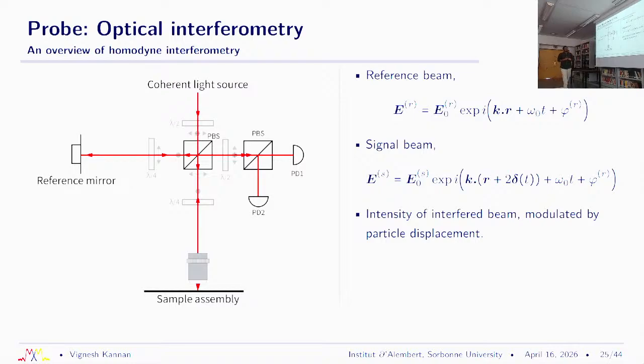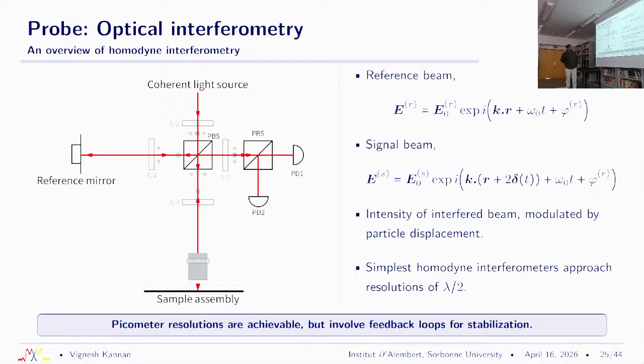Now the catch with a homodyne interferometer is unless you stabilize two laser beams, right, these are laser beams, unless you lock them to a particular phase, it's very difficult to get spatial or displacement resolutions less than half the wavelength of the light source we use, which is about 300 nanometers for us. 300 nanometers resolution is not acceptable for our experiment because the excitation is on the order of 1 to 10 nanometers. In principle with a homodyne system you can actually achieve picometer resolutions, but it involves a feedback loop which is a little complicated. We're actually moving towards that direction right now.